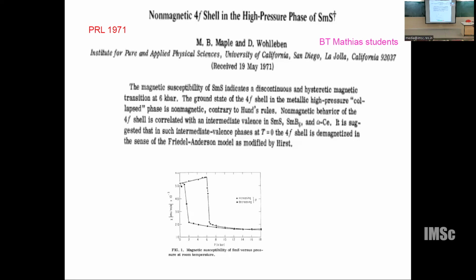So for the first time I realized the valency can be intermediate between two valence states. Not a simple valence change, but somewhere intermediate, fluctuating: the electron goes out and comes back. How do you get intermediate valence? The time average is fractional. If you measure photoelectron spectroscopy, you'll see both the valence states. So the time scale is involved. You measure through Mossbauer, which is a slow technique, and you will find an average. Susceptibility is a sort of average too. So it depends upon the technique which you use.